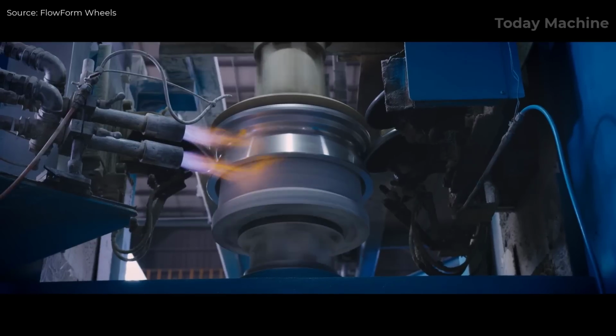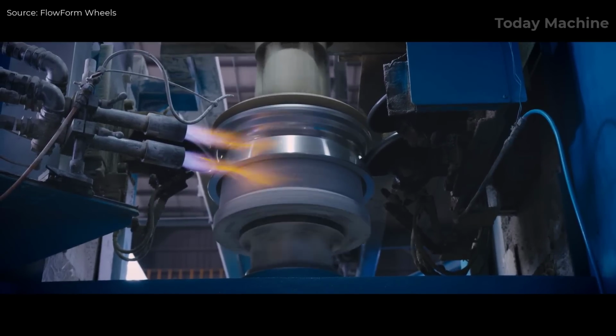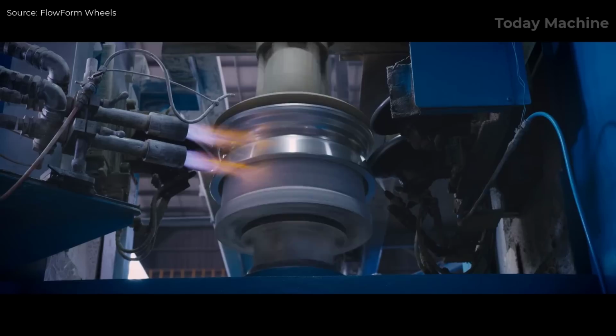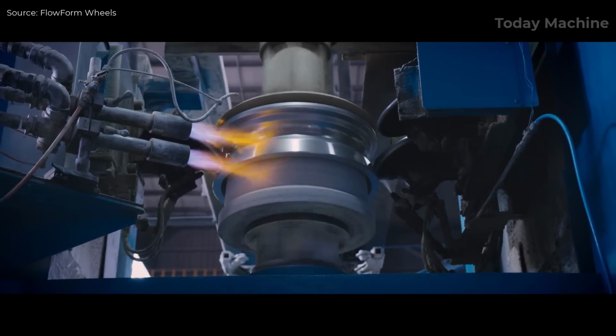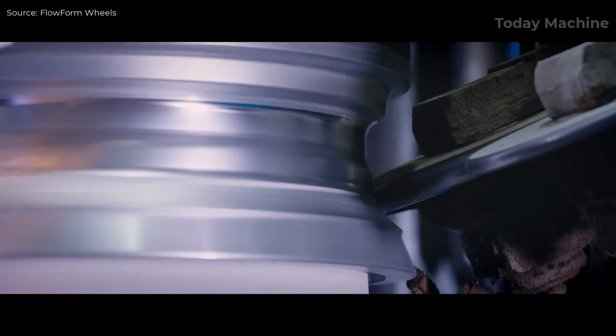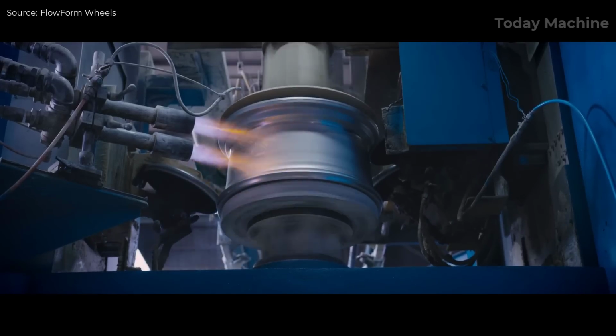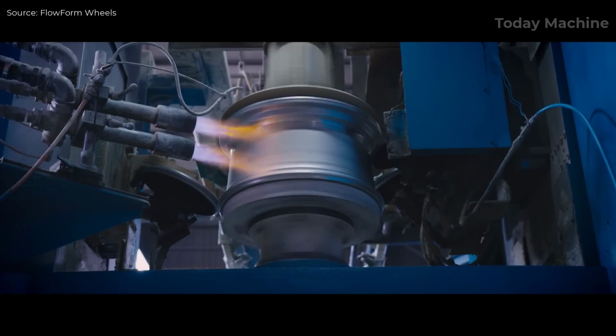The heated casting is then placed onto the mandrel, where rollers slowly press the aluminum skirt into the final rim barrel shape, stretching and squeezing the material in multiple passes. This process refines the metal's crystalline structure, enhancing the wheel's strength and its ability to absorb impacts more effectively than fully cast wheels.